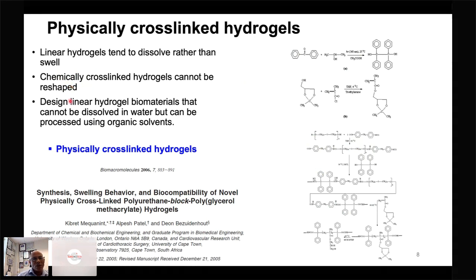And so the approach that we have used is to design linear hydrogel biomaterials that cannot be dissolved in water, but that can be processed using organic solvents, meaning that something that swells in water, but if we want to use organic solvent to process it, we can process it. We can shape it, and then if we don't like that particular shape, then we can redissolve it, or we can heat it up a little bit and soften it, because it's physical crosslinks, and those crosslinks can be easily broken, and then you can prepare physically cross-linked hydrogels.